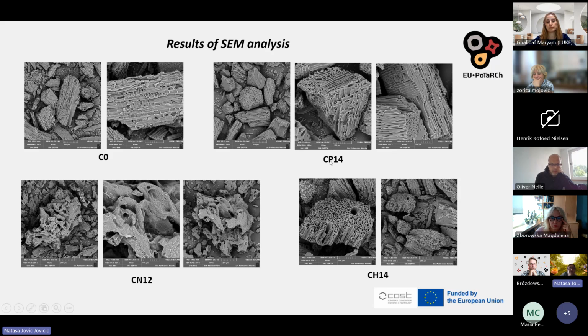The sample with phosphoric acid displays a highly organized, fibrous, and channel-like structure, possibly due to the specific activation method, and the surface is more open and fragmented with visible macro-scale cavities and cracks, indicating enhanced surface texture, although the micrographs of SEM analysis don't reveal micro and mesopores. The structural openness could contribute to better mass transfer in applications such as adsorption, or it could also be important if these materials were used as a catalyst.